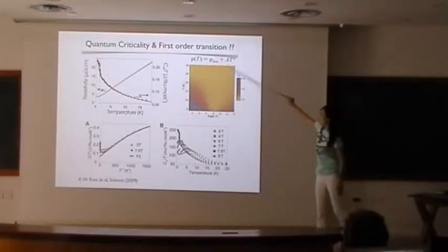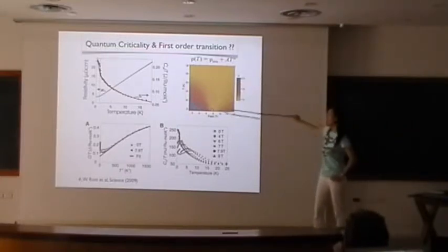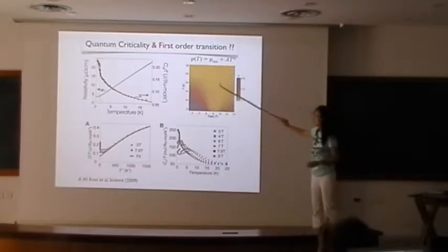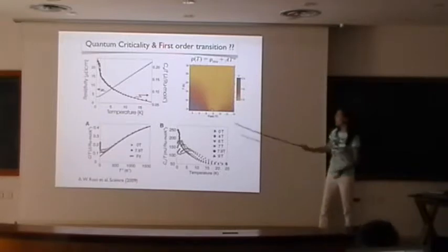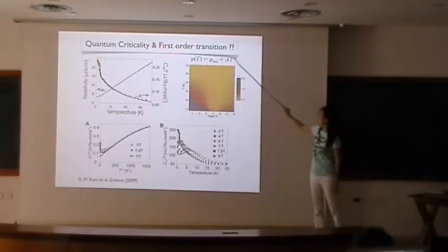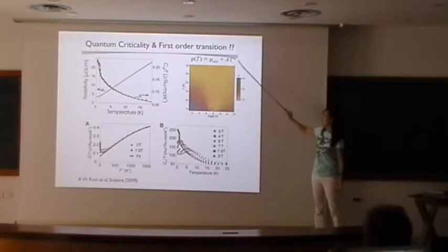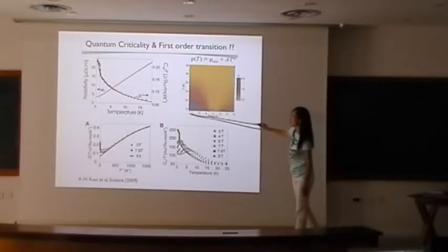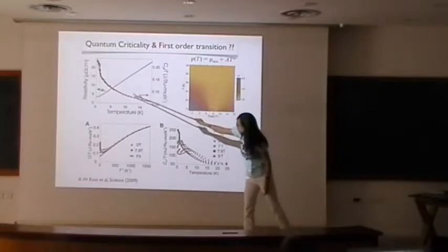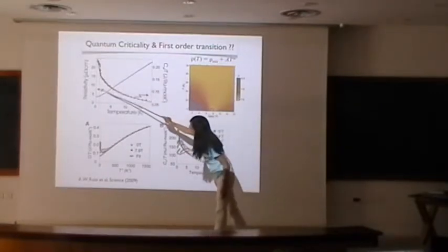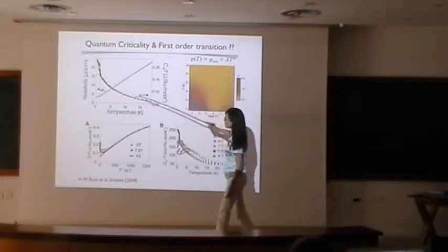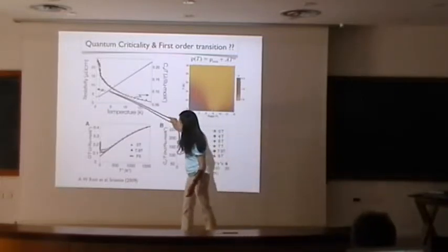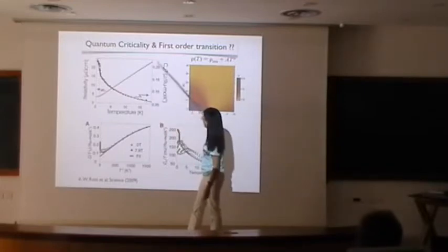Okay, so remember that I told you about the quantum criticality, and even when the system is ultra clean, at finite temperature this critical behavior still remains, like a residual resistivity T to the alpha, instead of Fermi liquid T squared. You get 1 here, 1.5, and this is where the Fermi liquid looks like. And not only the resistivity, which is this one here, at a field of about 7.9 Tesla, where the resistivity is linear up to some temperature.